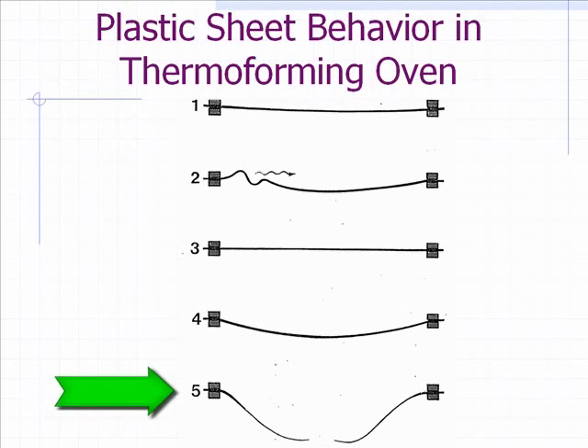And there's wide mesh screens over the oven elements, but if the plastic hits that screen, it'll get stuck there, and then if you leave it there, you can actually start a fire. So when you're running the thermoformer in class, you want to make sure you get it out when it's here and not like that. Especially if it starts coming out and it gets caught on there, it just makes a big mess. And you have to take that screen material, which is kind of a pain to get out of there, and take it outside and get the torch out and burn all the plastic off of it. That's about the only way you can get it off of there, is by burning it off.